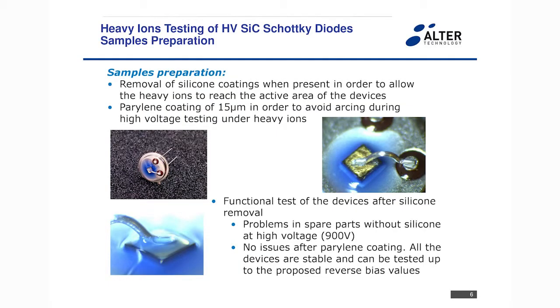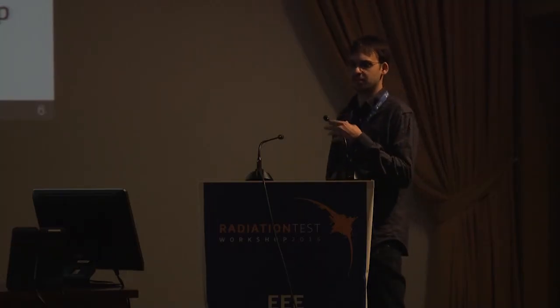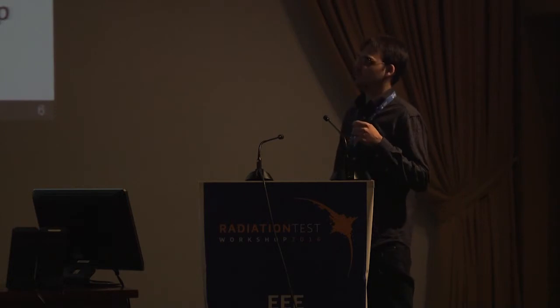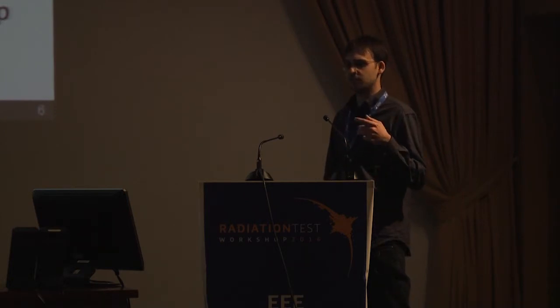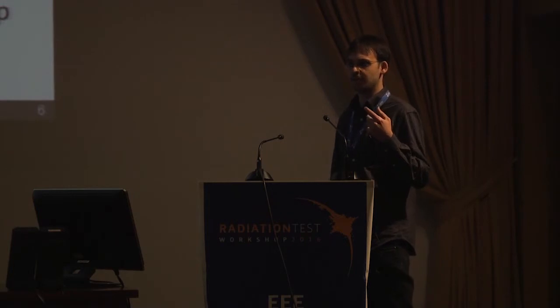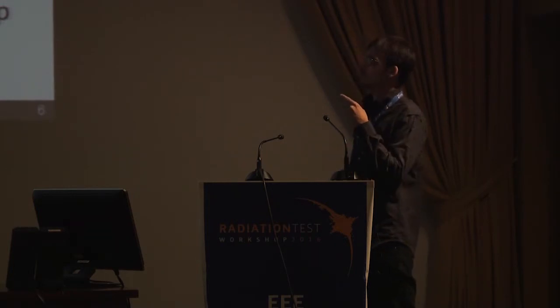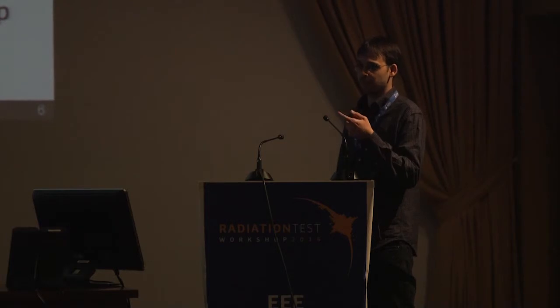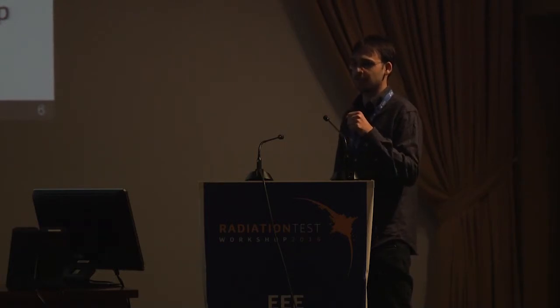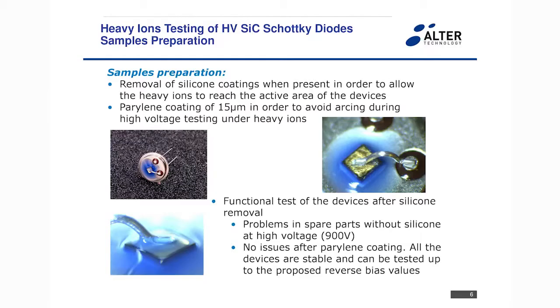Okay, well, this has been explained in some presentations yesterday. In order to perform the heavy ions test, you have to remove the lid of the device, and also the coating gels that these high voltage devices might have. We also want to test the heavy ions under high voltage biases. So that gel on top of the die was there for a reason, to isolate. So if you remove it, you can have discharges and damage the device without any heavy ions needed.